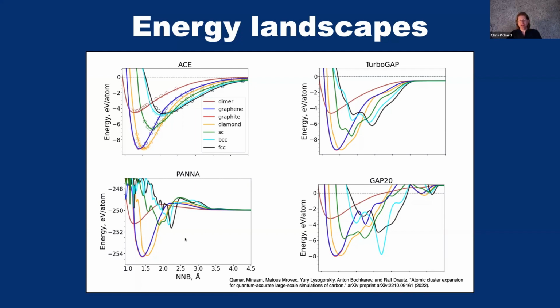So what's happened in these plots is you've taken a bunch of different structures, say graphite, diamond, simple cubic, BCC, and you've just swept through the lattice parameters. You've monitored how the energy is varying as you sweep through those lattice parameters. And physically, that should be a smooth curve. But what you're seeing for these machine learning potentials is that they work quite well near the global minima for diamond and graphite and so on. But as you move away from that, and also for other crystal structures, you have very rough energy landscapes. This would cause, to me, when I'm doing structure prediction, the kind of problem I have with a Tersoff potential. So it's not acceptable. I need smooth potentials.